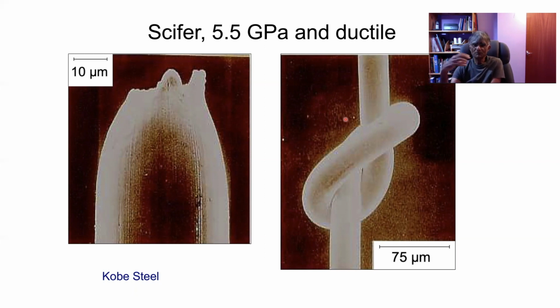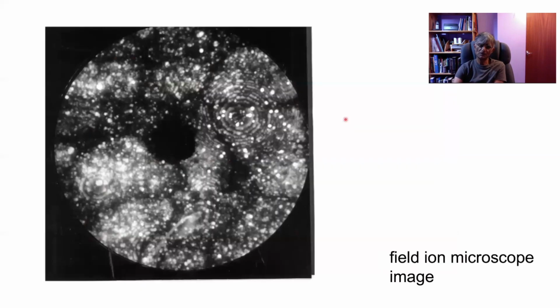Now, the problem is that in order to get this level of strength, you've got to deform it so severely that there is a very large dislocation density in the material, and the regions which are coherent inside this wire are very small indeed. To get that level of strength, if you imagine that you've got 60 grams of iron and you stretch it out into 2 kilometers, that's the level of deformation that's put into this wire by drawing. So if you look at its atomic structure using a field ion microscope, where every dot represents an atom,